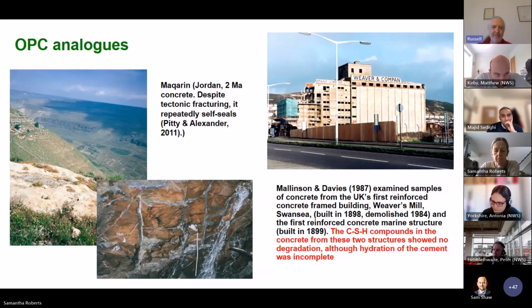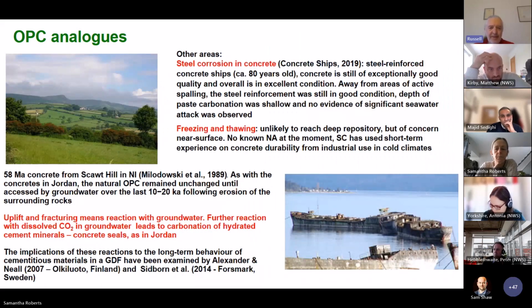Next one, please. Other OPC analogues. The one on the left, that's Scawt Hill in Northern Ireland, again from Tony Milodowski from BGS. This is nice because it's 58 million year old concrete. And a bit like the stuff that we looked at in Jordan, when it interacts with groundwaters, it tends to seal itself naturally. And it was completely sealed up until about the last ice age, probably, when erosion exposed it. But the areas that have been exposed and accessed by groundwater have sealed themselves really rather quickly.